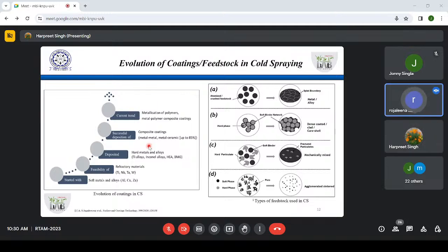Actually, sir, my research work is on pressing pellet formation, about 1 inch pellets of high temperature metal oxides. Not exactly coating; it's ceramic pellet formation by cold spraying. See, again, ceramic is very brittle, so pure ceramic pellets you can't make by cold spray. But if you add some reinforcement, like metal, ceramic up to 85% is possible. So if you have some ceramic, say silicon carbide or something of that sort, you have to add some metal binder into it.